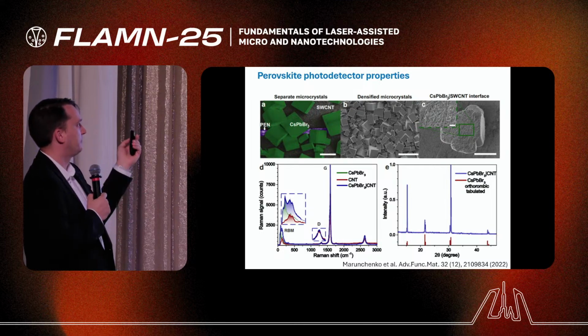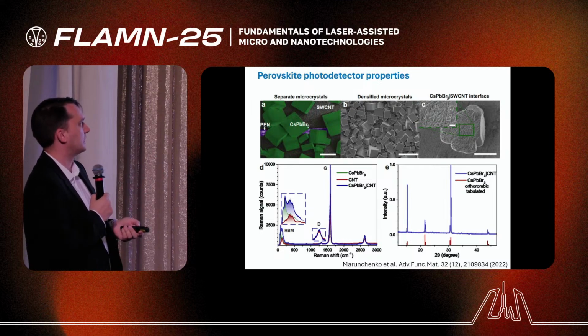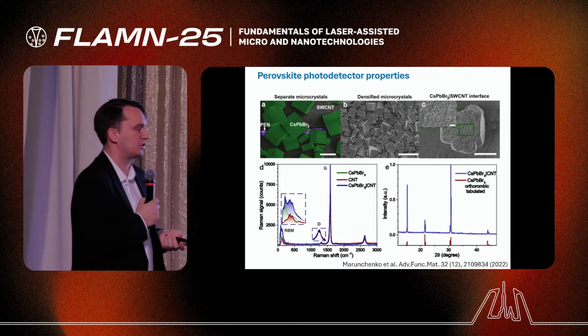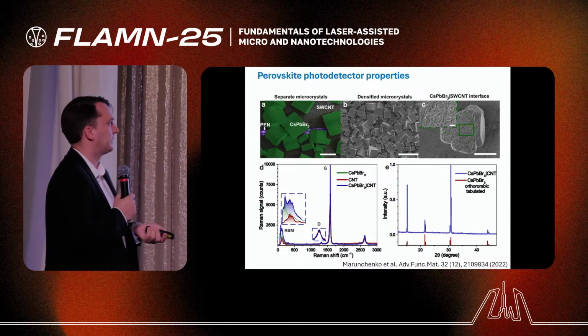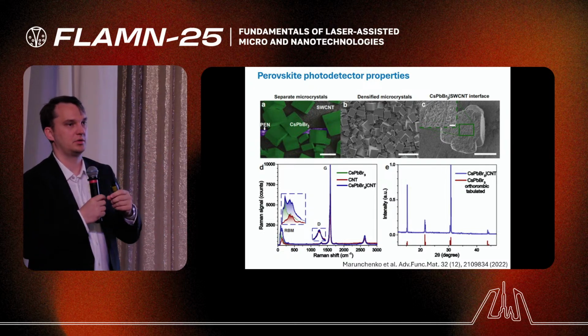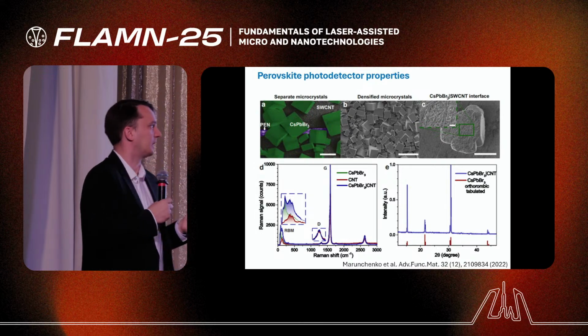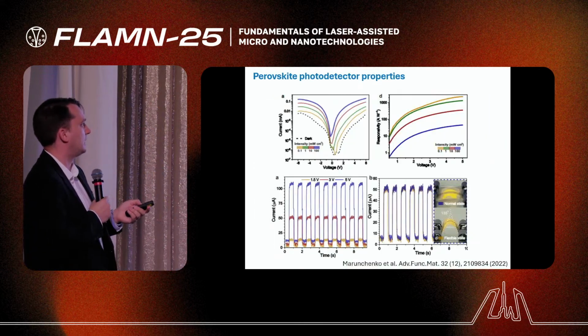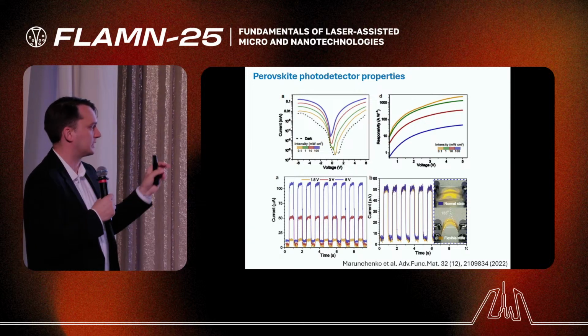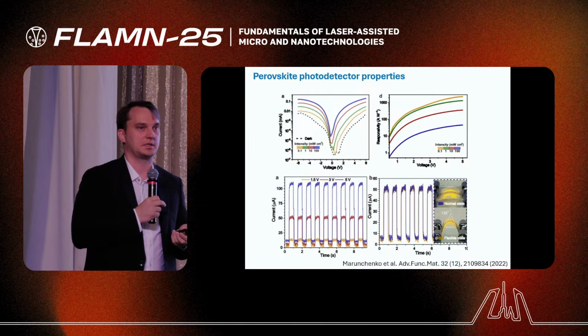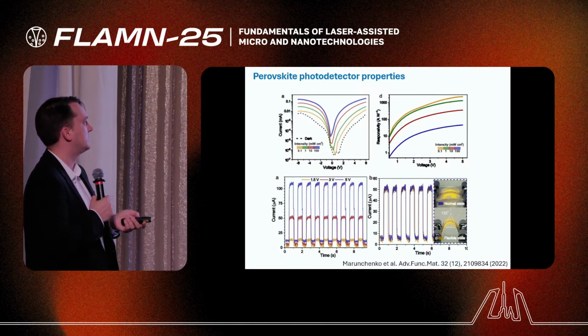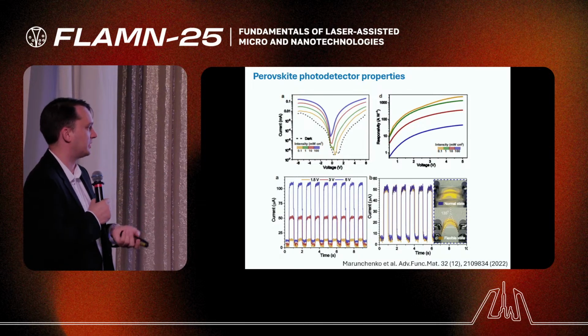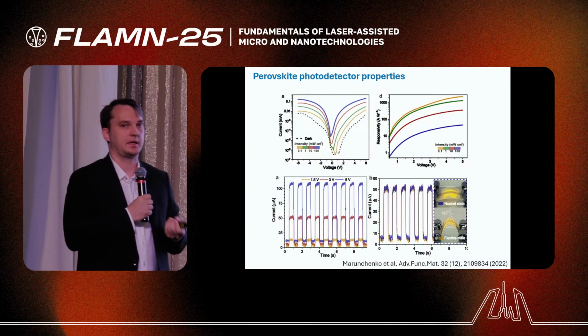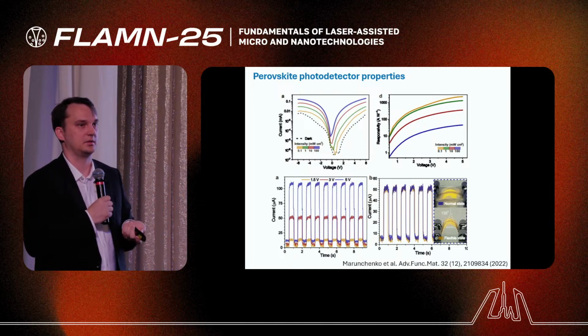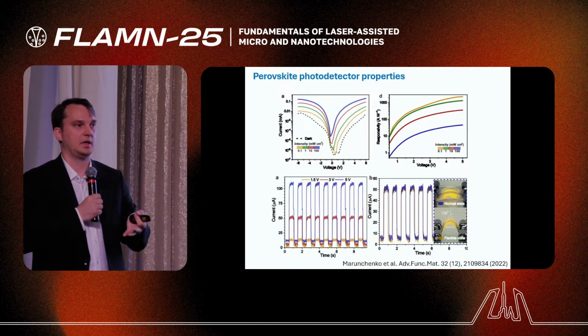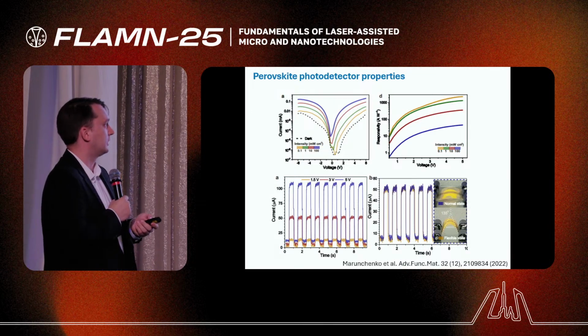Here you see these big formed microcubes. The size of each cube is around 10 micrometers. After growing, the contact is very good because they grew on top of these nanotubes, and the quality is quite good. Then we created such a flexible photodetector with quite good responsivity and reproducibility. After many bending cycles, this device is still working well because of the very good contact between perovskite and the single-wall nanotube film.